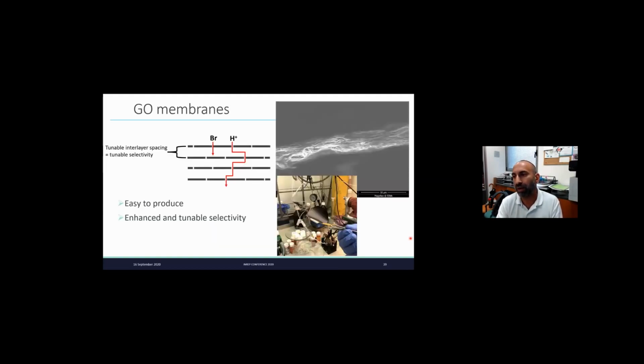So we also thought about using this kind of approach to modify the membrane, because that's also something you can think about, not to protect the catalyst itself, but to block the bromine diffusion on the membrane. So what we did is to use a very simple separator and to put on top of it some graphene oxide. So this is the membrane that we got. This is a cross section of the membrane. It's about 4 micron thick.